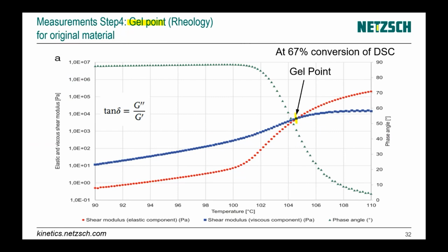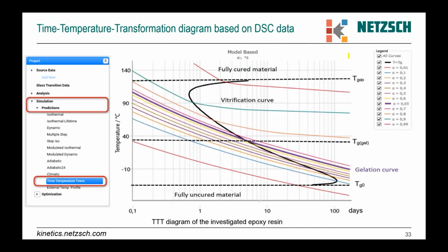And we can find from DSC data with the same temperature conditions that for this temperature we have 67% of conversion. It means that for our chemical system, the gel point corresponds to 67% of conversion, and we can use this value for the simulation of our time temperature transformation diagram.